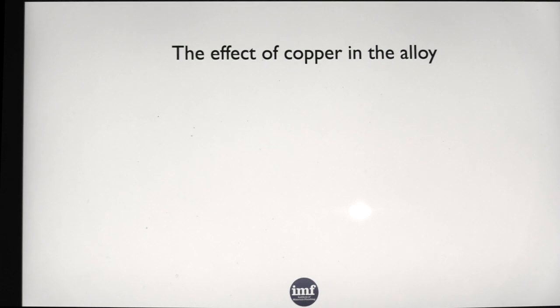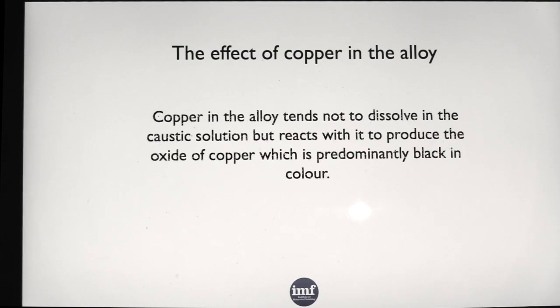So let's look at the effect of copper in the alloy. It tends not to dissolve, but it produces this predominantly black colour, and it seriously can be black. I mean, it can be as black as that. Completely jet black. In fact, if you go into the printed circuit board industry, they deliberately produce black copper oxide so they can stick boards together. It's got a lattice on it, and it can anchor glues and things like that and stick together. Not very good for electroplating though, unfortunately.